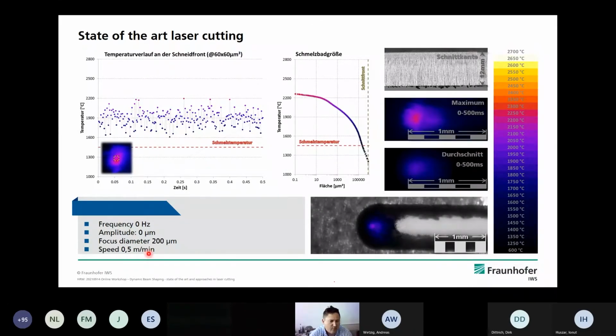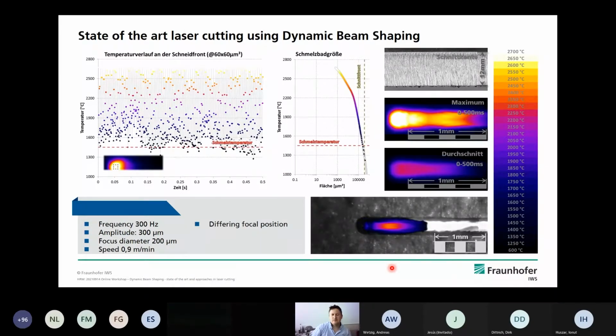Please remember these parameters, we are not using dynamic beam shaping. Our focus diameter is 200 microns, and the process speed for this cut is half a meter per minute. Please keep your eyes on the width of this cut curve. If you are using dynamic beam shaping, you are able to use a special focal position, a quite higher focal position, which allows us to achieve a smaller cut curve.